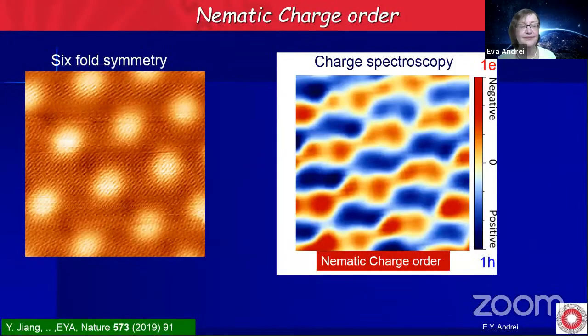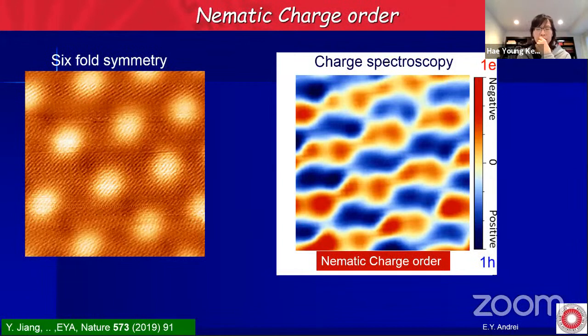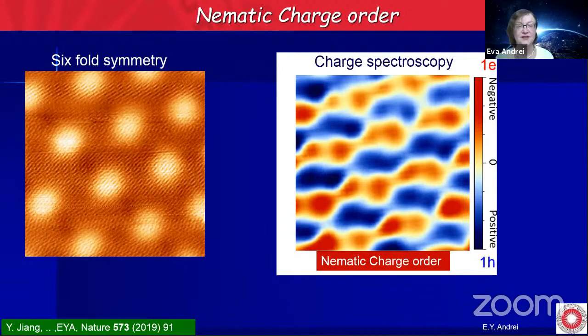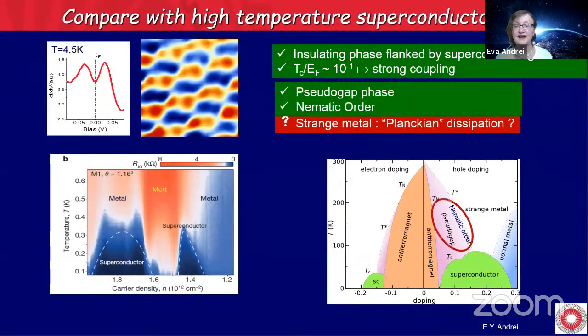Okay, so what we have seen with the scanning tunneling microscopy, we're able to actually, this is the topography, we're able to measure the local charge, and we've seen that when the Fermi energy is within the flat band, we get this nematic order. Just like in high temperature superconductors, there is nematicity in the pseudogap phase. Here we have a pseudogap, and in the red regions we have 1 electron per Moiré, whereas in the blue regions we have 1 hole per Moiré. So we have alternating stripes of positive and negative charge. And this is spontaneous, and it only happens when the Fermi energy is within this flat band. When we are outside of the flat band, it doesn't happen.